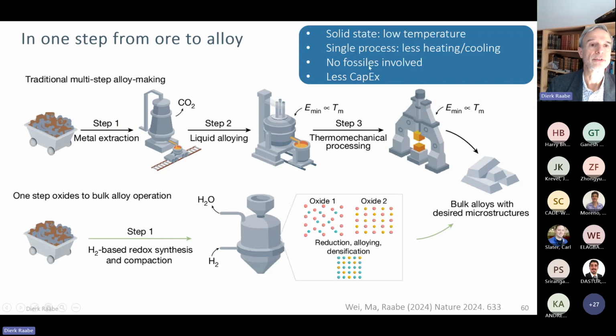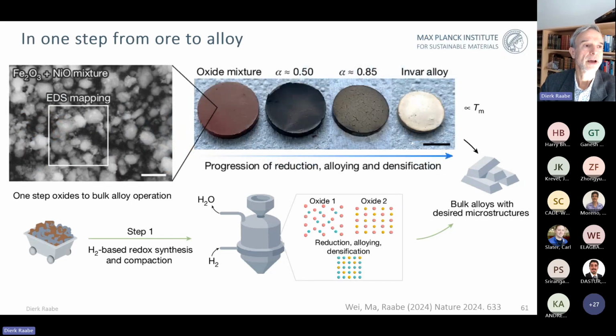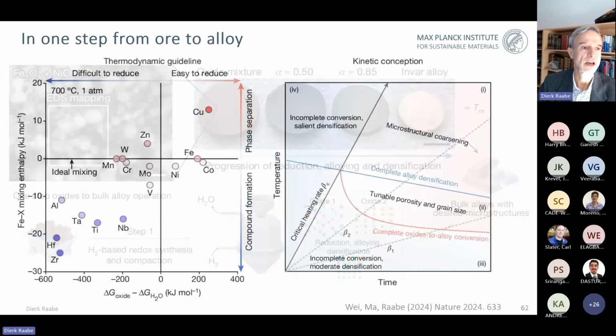That means you can do everything at low temperature in the solid state. You have a single reactor. You don't need to include any fossils and have, of course, smaller capex requirements and so on. And you can arrive at decent sample sizes in these lab scale experiments. We have chosen a very simple example, namely a nickel iron alloy, the famous Invar alloy, to demonstrate that this really works, plus the densification.